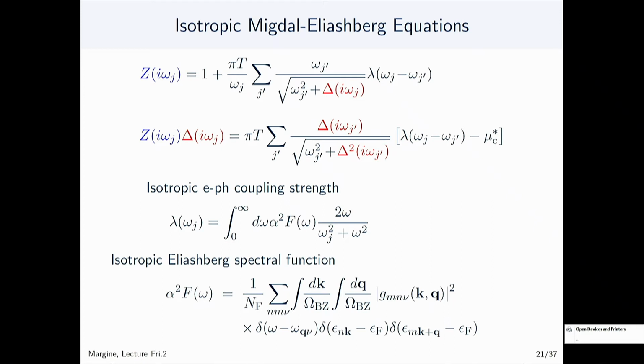So in the McMillan expression, you just have this mu star equals zero, and now you should be able to recognize the electron-phonon coupling strength. And the same here, this is just the isotropic Eliashberg spectral function. As I said in the beginning, the McMillan Tc, later refined by Allen and Dynes, was found as a solution, or basically fitting through data obtained by solving the isotropic equation for some specific materials. So it's just an empirical fit through data obtained by solving these equations.